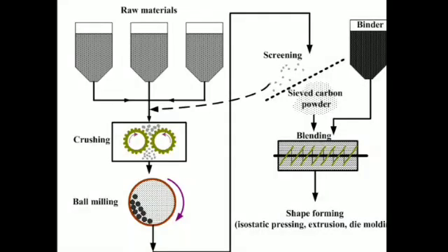Now, graphite is artificially produced by heating powdered coke, and coke is another allotrope of carbon only, an amorphous allotrope. This coke is heated with a small amount of sand and ferric oxide in an electrical furnace at a temperature of about 3000 degrees Celsius.